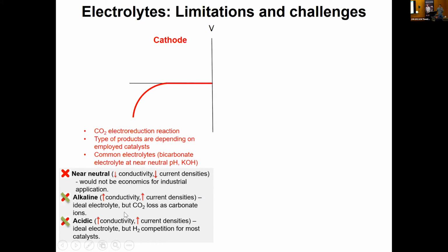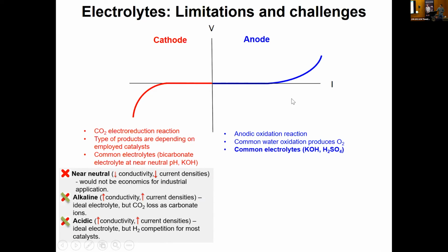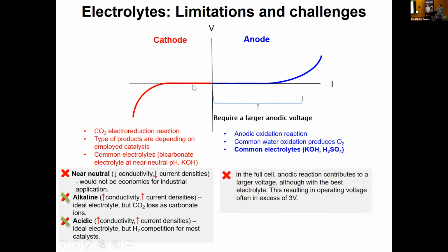Of course, the cell is not only one part; the anode part is also important, right? And that also contributes quite a large, higher voltage. So in this case, if we use a water oxidation catalyst in alkaline, usually we need about 1.5 volt. So when you end up with the cathode, to get high current, it's usually in excess of 3 volt. And that again limits the economics of the reactions.